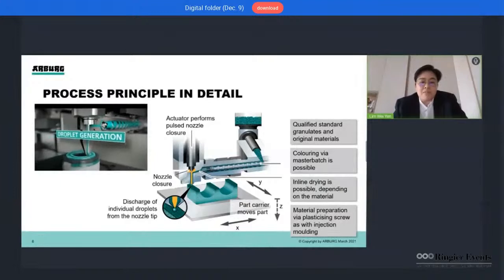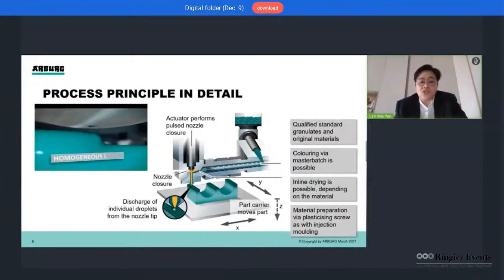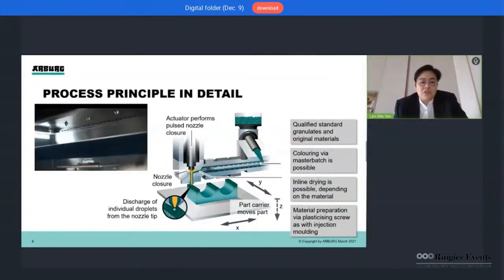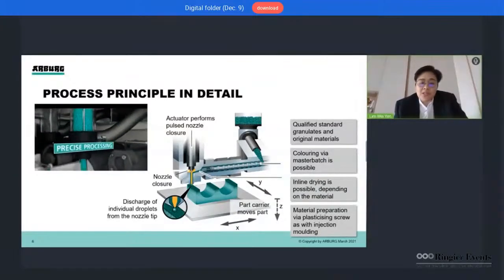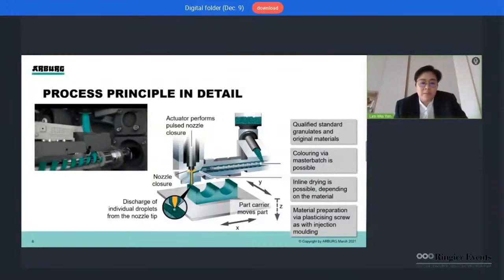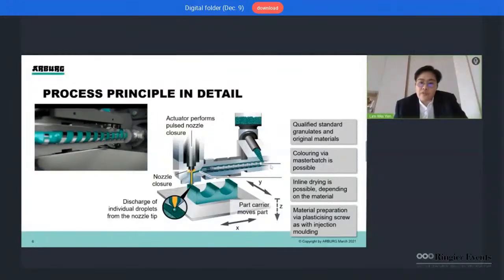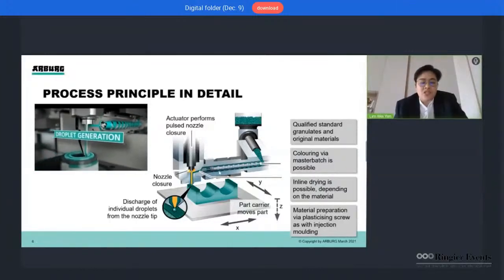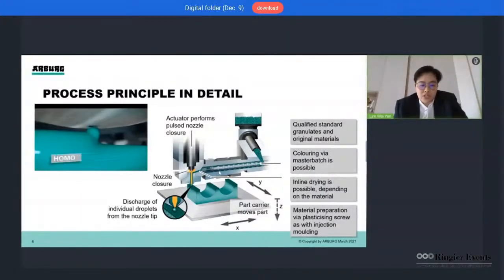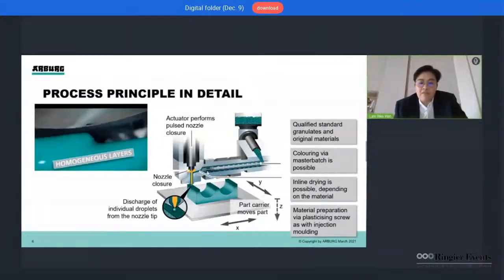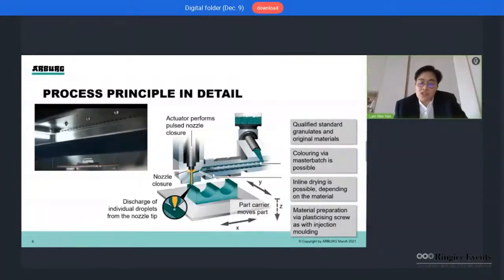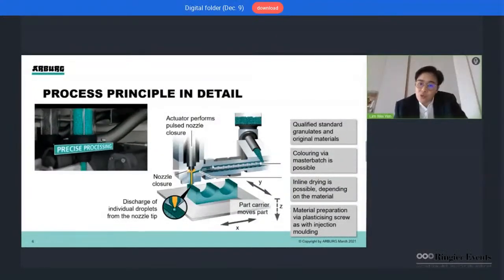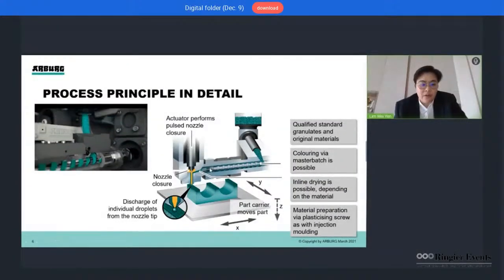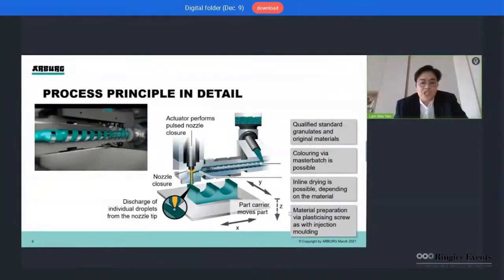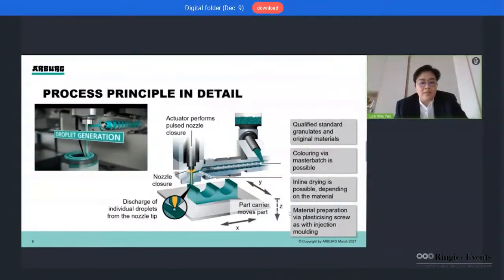The plastic melt is then pushed towards the nozzle and is discharged as a string of droplets by opening and closing the nozzle. The melt material necessary to discharge the droplets is generated with a forward movement of the plasticizing screw over here, and the precise, reproducible discharge is enabled by a non-return valve that closes the screw as the screw advances. The non-return valve is located at the front tip of the screw over here.